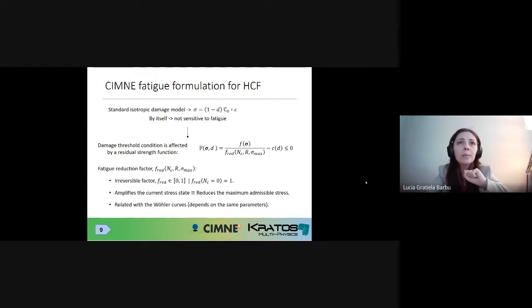So a little bit more detail about this reduction function. Basically, it's an irreversible factor. You cannot go back, you cannot recuperate it. It starts at the beginning of a simulation when you have a virgin material with a reduction coefficient of 1. As you advance and apply a number of cycles, you progressively lower this coefficient. The effect it has inside the damage threshold condition is that it amplifies the current stress state until you reach the threshold and go into the nonlinear domain, or you can see it as equivalent to reducing the maximum admissible stress inside your material.